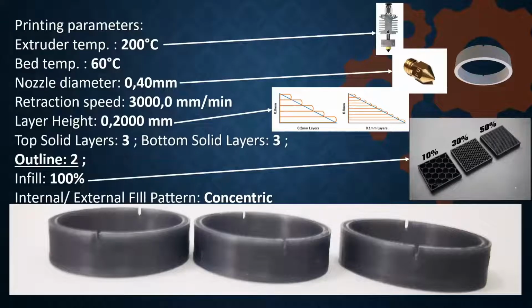Okay, you can see the printing parameters on this slide. And what I would point out is the number of outlines. In a test performed on the SENB specimens, it was proved that at the number of outlines 2, the crack propagates in the desired direction from the top of the groove. There is no possibility of delamination due to insufficient crack length applied to the test specimen.